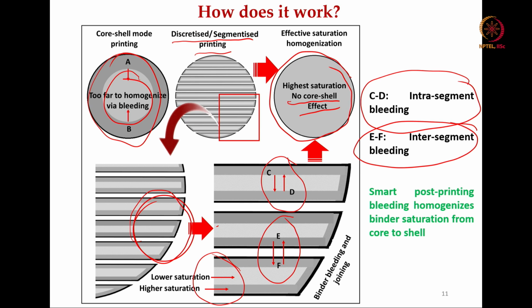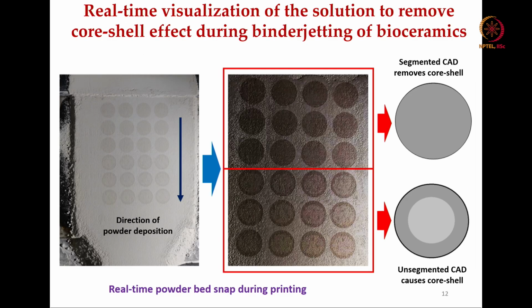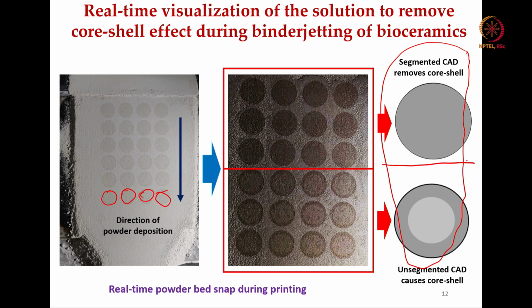This aspect is very well proven in our study. You can see that we have taken these photographs during the binder jet 3D printing. You can see zirconia based materials, where these separate zirconia based materials were getting printed. It is the initial stage, it is almost at the final stage, and then the segmented CAD model essentially was used to remove the core shell mode of printing. This is the segmented core, this is the unsegmented CAD, which causes the core shell.